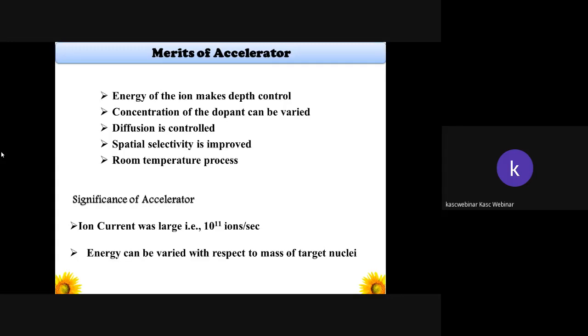Then what are the merits of that particular Pelletron accelerator? The energy of the ion makes the depth very easily controlled. Then the concentration of the dopant can be varied, and the diffusion is controlled, and the spatial selectivity is also improved as expected, and it's also called a room temperature process. And the significance of these particular accelerators is that the ion current is very much larger, 10 power 11 ions per centimeter squared per second can be dropped over there. Then the energy can be varied with respect to the mass of the target nuclei and also the charge state of the target nuclei.